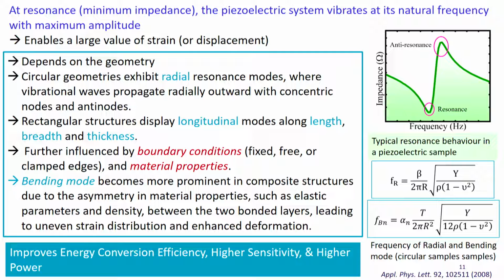Once you make the device, you go through the impedance spectroscopy for that. Here the impedance spectroscopy becomes a very important factor. You see the impedance spectroscopy, identify the resonance modes in it, and then try to play with that. If you are able to change the material properties, fine. Otherwise you have to change the compositions and other things to do the modifications.